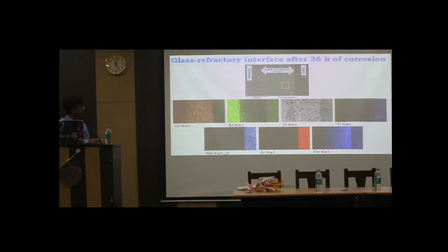And near the uncorroded refractory, the aluminum concentration is more, and near the glass side, the aluminum concentration is less, but in the glass, there is aluminum. So that means aluminum is migrating from the refractory to the glass. And then oxygen, titania, more or less it was there, in the glass side it is more, but the sodium is the same.